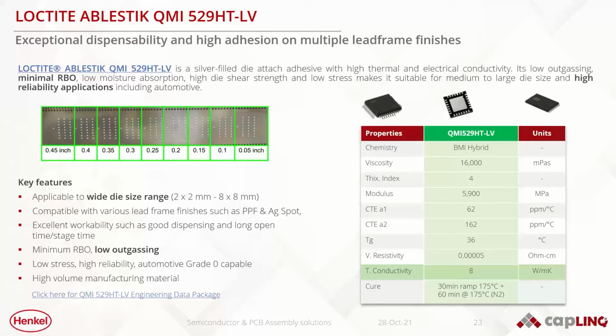So the QMI529HT-LV is actually a silver-filled die attach material. The HT stands for high thermal conductivity. And the way that you get this high thermal conductivity is that you stuff it very full with silver, which gives it very good thermal conductivity. The problem, of course, is that you have a hard time dispensing it.